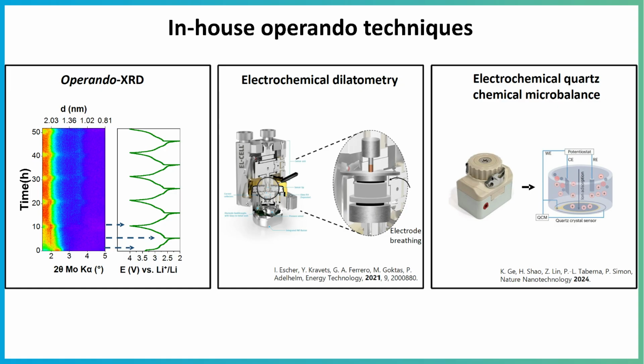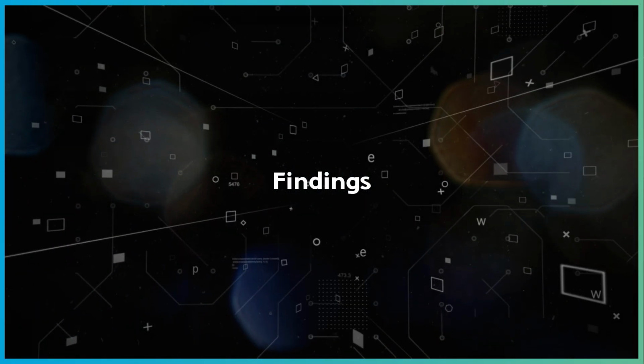inside your V2O5. Finally, we collaborated on simulations to identify the dynamic interaction between the intercalating ions, the pillars, and the host lattice with different interlayer spacings using molecular dynamics simulations. First, we investigated how the pillars interact with the host, and we found that the amines from these diamines get protonated. So they are not amines in the end, they are ammonium ions, basically alkyldiamines, which get protonated, and they ionically bond with our V2O5 host lattice.